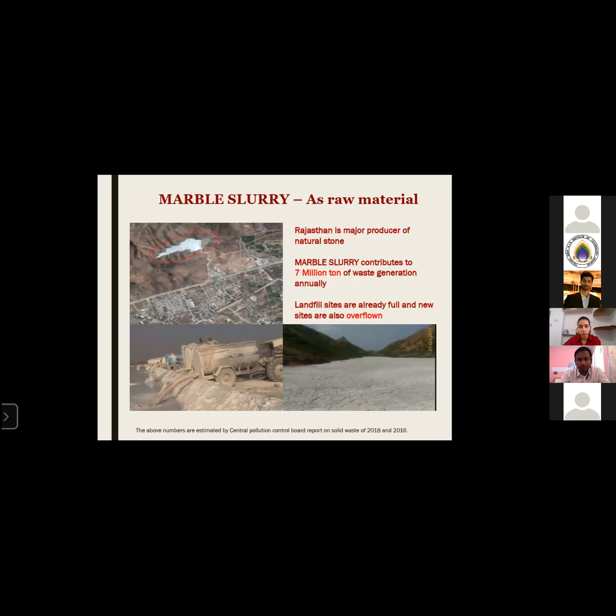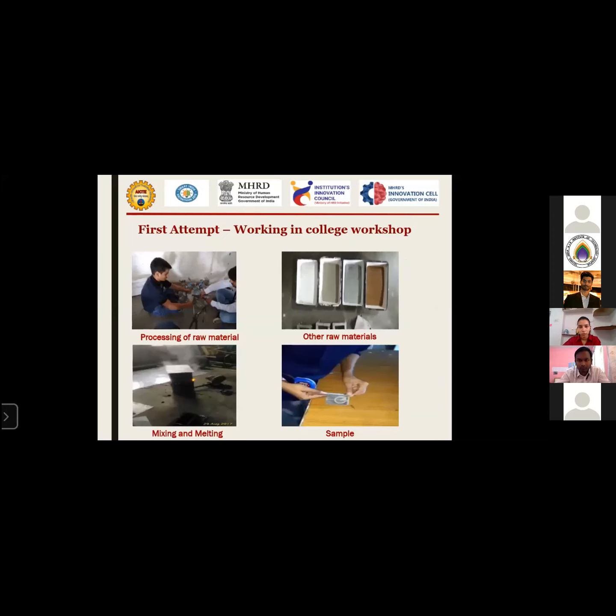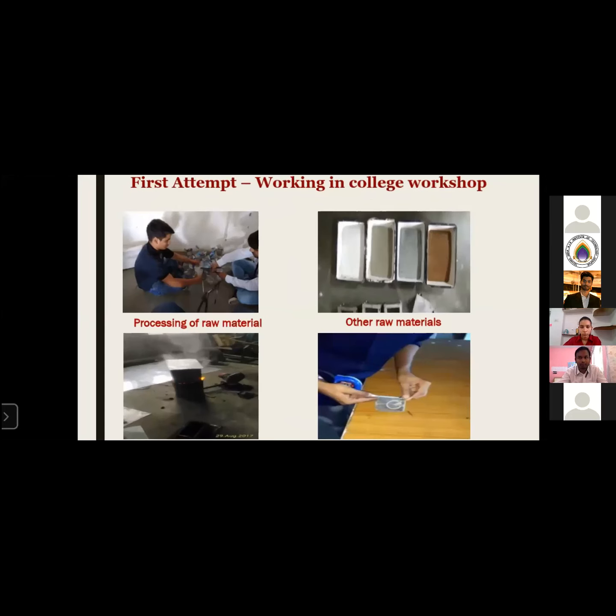We took this sample to our lab and started working on it. The plastic bottles we collected from a scrap dealer, and we collected this slurry from the landfill site. And here in the third picture, you can see the first attempt. We tried with this tin oil container, and we added all the material into the tin container and fired it.